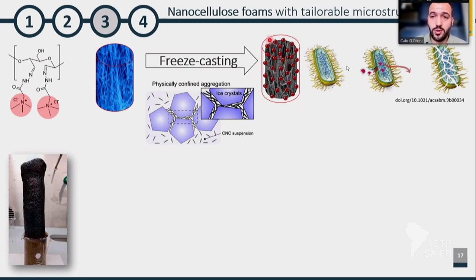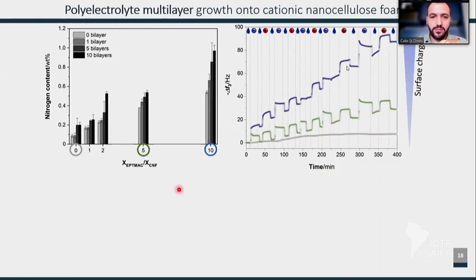But we use this as a substrate, as it is positively charged, to grow multilayers of oppositely charged molecules, particles, you know? So this is what we call the layer-by-layer assembly of multilayers, which is quite typical. You've seen this, right? So we can play with the surface charge. The more surface charge we have, the more the adsorption of the oppositely charged layers, right? So this is a typical QCM-D measurement. As mass is adsorbed onto the substrate, the frequency changes, right? It decreases. There is a minus here, and you can really see the mass adsorbing.